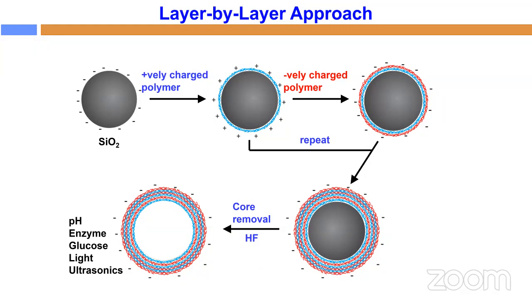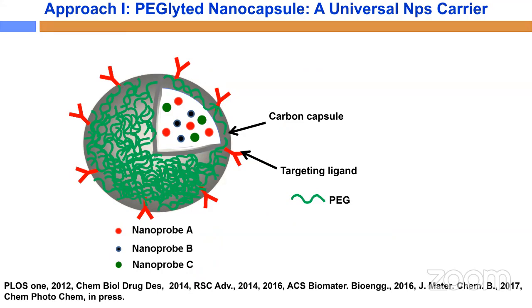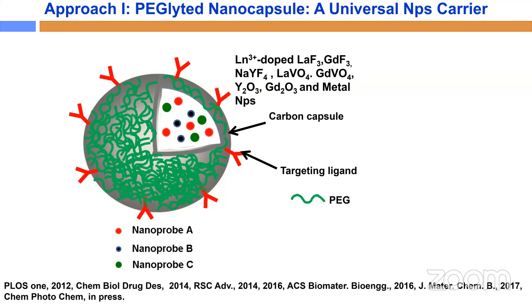Now what we did is take this polymer capsule and put it into the nanoparticle precursor, for example a gold salt. The salt has ions, and the polymer capsule walls are porous, in the sense that they allow only the ions through. So it will react within the cavity of the polymer capsule and the nanoparticle will be formed inside. When the particle grows and attains a certain size, it cannot come out. You just centrifuge the polymer capsules and remove the supernatant, where all the bare or unencapsulated nanoparticles are present. Then you do the further surface treatment for PEGylation and the antibody. In this way, we can load multiple types of nanoparticles inside the polymer capsule.